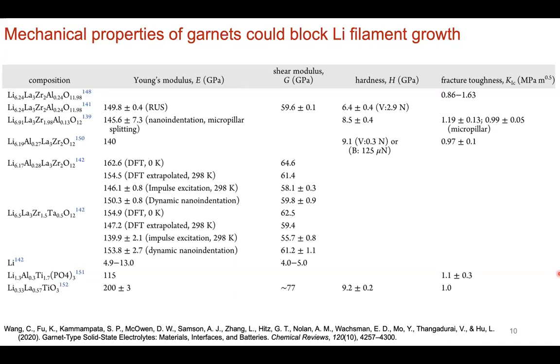In terms of experimentation, there's a lot of work that's been done already, not even looking at the atomic scale of how these filaments grow, but really just the wetting properties of lithium onto these oxide-based materials, and how to better wet lithium onto these oxide surfaces and how to better coat them. I only have one slide on that, but the body of literature is quite vast on that within the last, I would say, 5 years on understanding wetting properties, because uneven wetting of course promotes uneven growth of lithium. So what you want is uniformity at the interface.